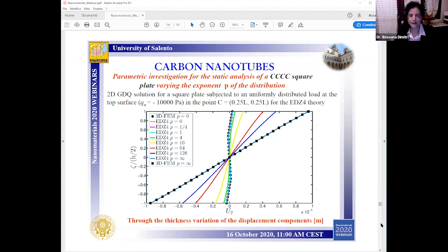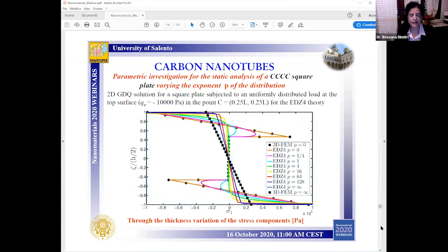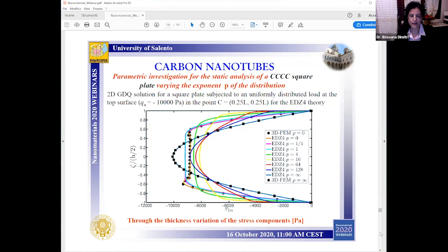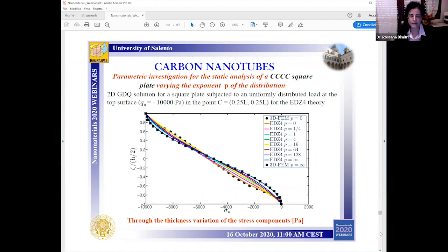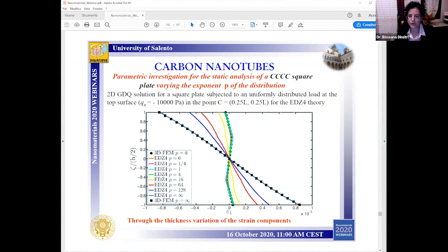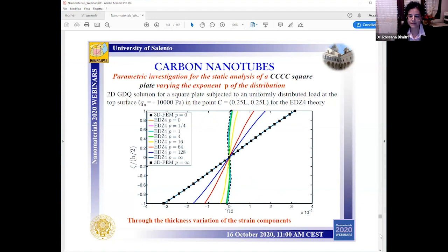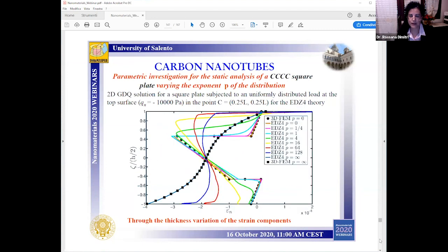So these are the other components of the displacement, and similar considerations can also be repeated when we analyze the variation of the stress components, I mean in-plane stresses here, and also out-of-plane stresses, as you can see here. So this behavior is also reflected in the strain field, as you can observe in these plots, both for the in-plane strain components and the out-of-plane components.